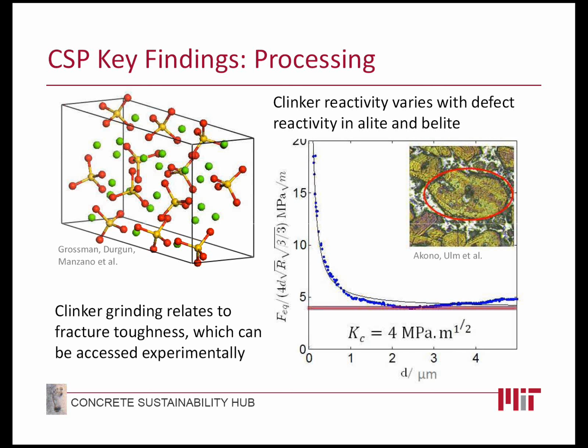Through the atomistic models, we now understand why, not just that they differ, which has been empirically known for a long time, but why, and then how we can modify that by introducing substitutional elements into the clinker, which is already done in practice, but not with any quantitative understanding as to why, and really make rigorous predictions of this, and then in partnership with the LCA side of our hub, be able to say, well, is that worth it? If we were able to make and engineer a new clinker, will that bring down the GWP of the roadway in a way that we can argue is a substantial advance? So this gives quantitative tools to guide your decision making.